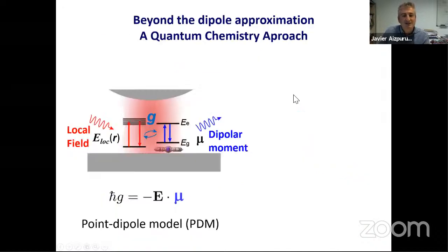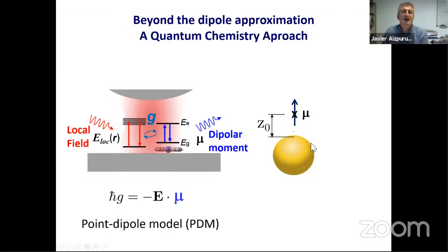And what happens in this description that I just mentioned of the exciton local field, plasmonic field interaction in this fashion is that most often in nanophotonics up to now, we have been using the description of this dipolar moment, the transition between the ground and the excited state, as a point dipole. This was the assumption, right? That this oscillation, this electronic transition, could be associated to a point dipole located somewhere, right? But one can imagine that this works for Fabry Perot cavities, for micro resonators, even for photonic crystal cavities.